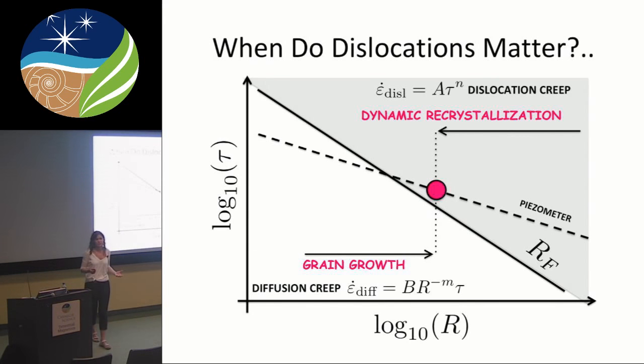This is an Arrhenius type of law. And so depending on the temperature will tell you whether your dislocation creep is a prominent deformation mechanism, whether the energy associated with the dislocations is high enough. So I would say that's why temperature would matter. We haven't explicitly tested it.